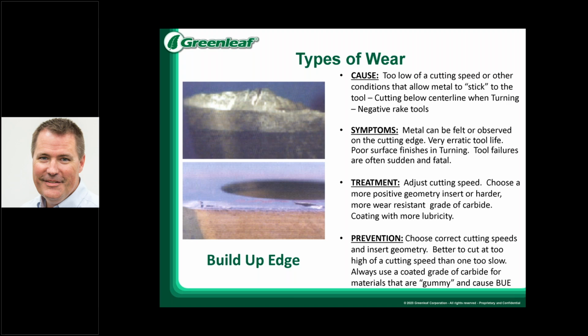Cutting speed is key for this type of failure or tool wear itself. Being able to run with a more positive grade with higher speed, and probably looking at a PVD coating for this type of operation as well. It will end badly if you continue to let it build up as shown in these images.